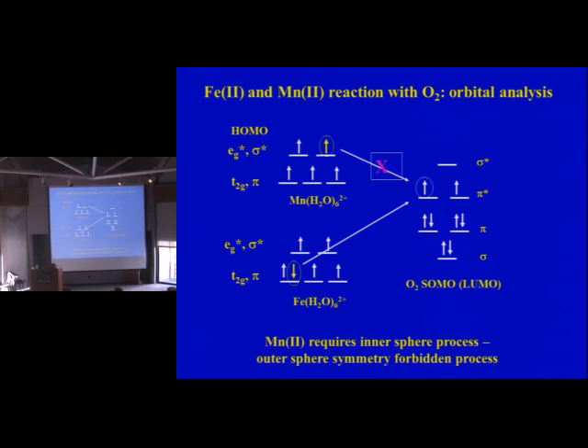We didn't try to do that. We could measure peroxide, for example. The way we've done that in the past, and it usually works when it's lower concentration than when it's at the maximum: the iron 2, the oxygen reduces in a mercury electrode in one 2-electron step to peroxide. Then that peroxide, which was formed by the electrode, then reduces to water. So you see a ratio between the peroxide signal and the oxygen. If, for example, the peroxide signal increased dramatically over what you expect it to be, you could actually say we have peroxide. We've actually seen that in salt marsh sediments at low oxygen content, all right?